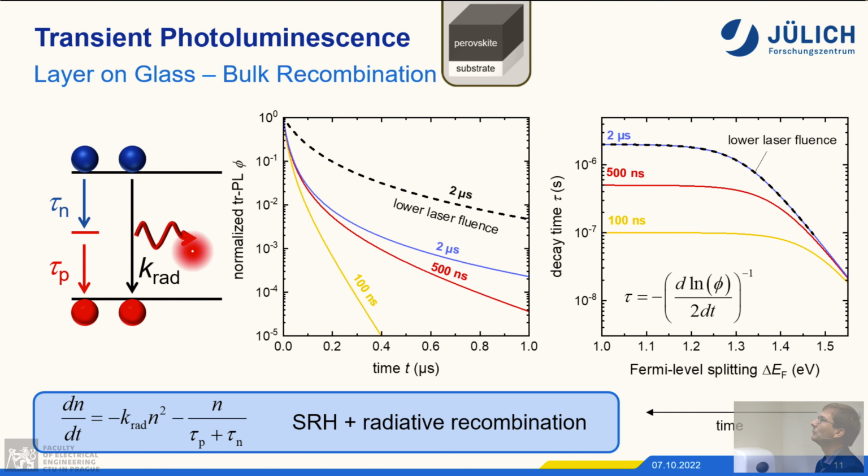And if you then measure something, it would probably look like this. Yeah, so at the beginning your quadratic recombination term is dominant, and at later times your linear term becomes dominant. At the beginning you have something that's not exponential, and then towards later times it becomes more and more exponential. Okay, so one way of now plotting this data is not to plot the raw data,